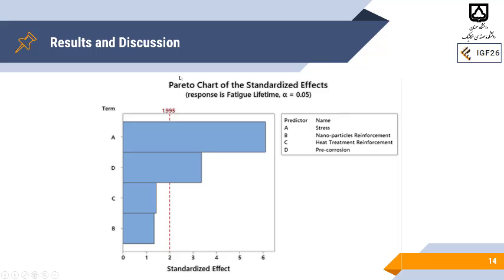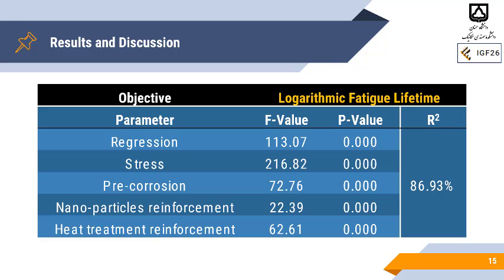Here you can see the Pareto chart. A is stress and D is pre-corrosion. 2 parameters are effective, and 2 parameters, C and B, meaning heat treatment and nanoparticle, have no effect. But this is not correct because the coefficient of determination was low. If you use the logarithmic scale for the fatigue lifetime, you can see the R2 value increased. It's about twice the previous value. So here we also have a proper p-value for the regression, and all parameters are now effective.